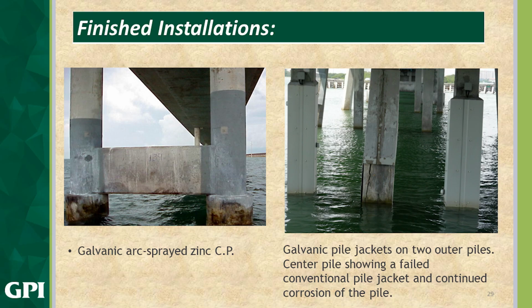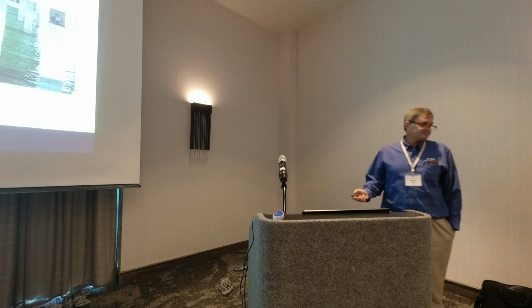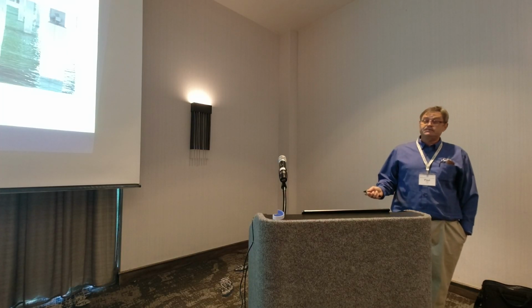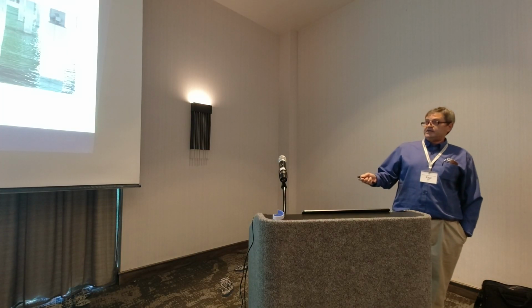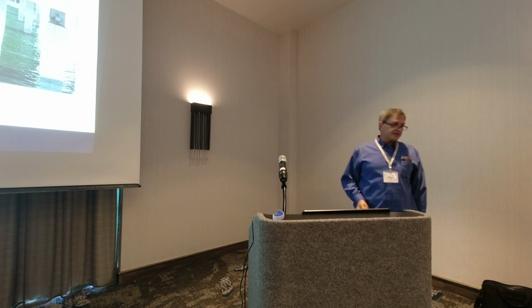Some more finished installations. On the left, we have galvanic arc sprayed zinc. On the right, we've got galvanic pile jackets on the two outer piles. We've got a standard conventional pile jacket in the middle, and as you can see, the spalling protruding through the bottom of that jacket. It's actually deleterious because we can't see how bad the corrosion is behind that jacket.